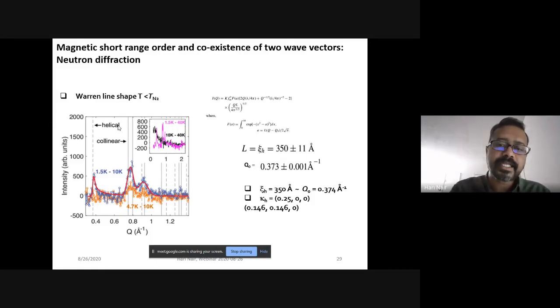And we see exactly similar behavior in our magnetic system, which means that our magnetic system is not actually completely long-range ordered, but there are some regions where the spins behave like a liquid. And what is the characteristic length of that liquid? It's about 350 plus or minus 11 angstrom. That's a correlation length.